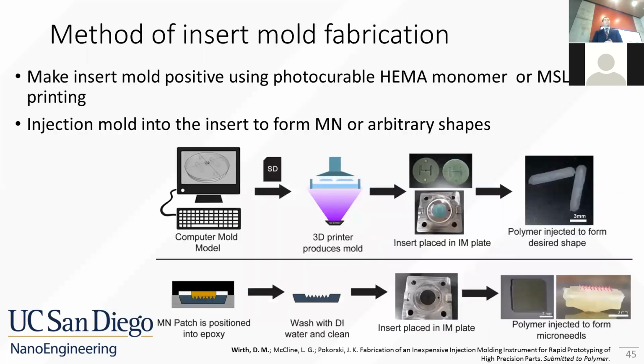The idea here is to have a conventionally machined steel plate to withstand the pressures involved in injection molding, and then have an additively manufacturable insert which fits into this plate to impart the final geometric structure. We can also use epoxy cast inserts to achieve a bit higher geometric fidelity.